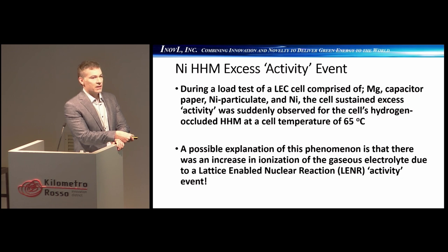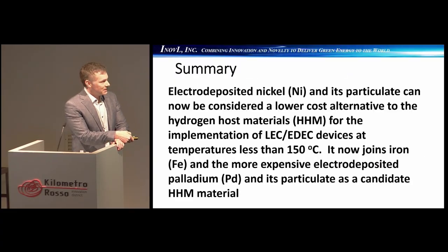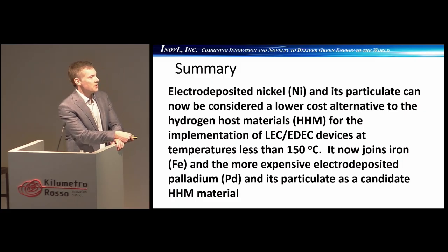And it is interesting to note that after this event happened, the cell worked much better at all temperatures that we tested it at. It had no problem getting into low resistances. So in summary, the electrodeposited nickel and its particulates can now be considered a low-cost alternative to hydrogen host materials for the implementation of LEC or EDEC at temperatures less than 150 degrees Celsius. It now joins iron and palladium and titanium as particulate candidates for HHM material.